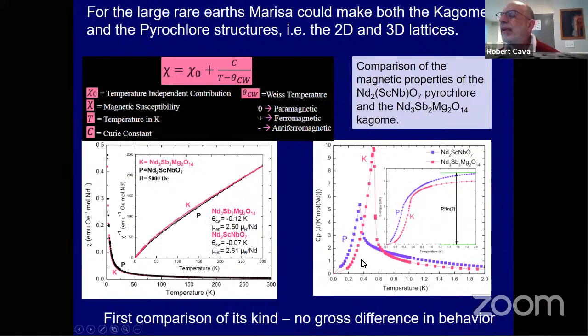The only thing that's different is if you look at the specific heat, you can see that the pyrochlore lattice loses its magnetic entropy over a broader range of temperature and at a lower temperature than the Kagome does. So adding that extra vertex makes things order at an even lower temperature. So this is like 400 millikelvin or something like that. It's a very low temperature. It's very annoying. It's so low.